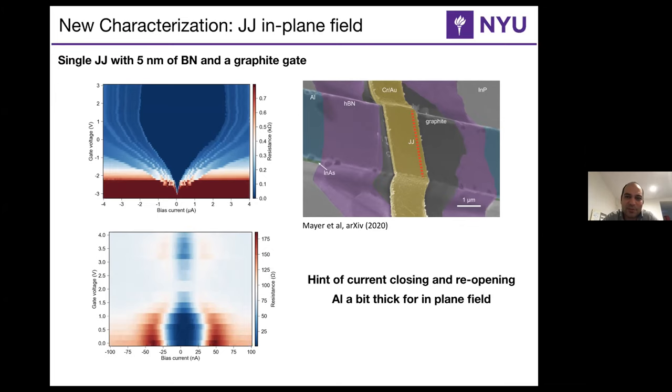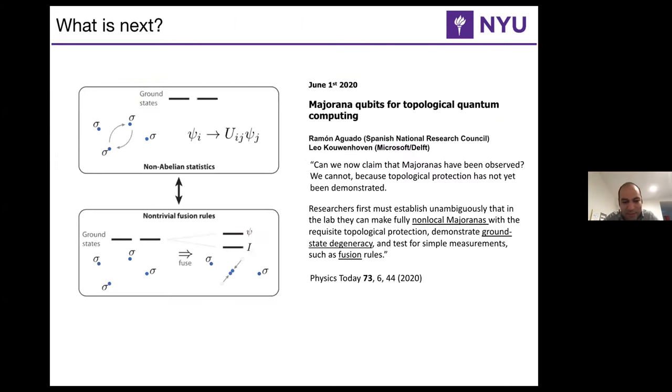I think this is interesting just because hBN has a completely different chemistry at the surface compared to aluminum oxide, right? So if something weird is happening at the surface, it should basically completely change the device characteristic. We also learned from this device that aluminum critical temperature and field highly depend on the thickness. So when we do ALD deposition, it apparently removes a few layers of aluminum, making it thinner. This is made on similar devices that we do ALD on, and hBN obviously doesn't attack the aluminum. So the critical field is around 650, 700 millitesla, while on the other devices we get quite a bit less. I wanna say this is about 12 nanometer, and the other ones are smaller.